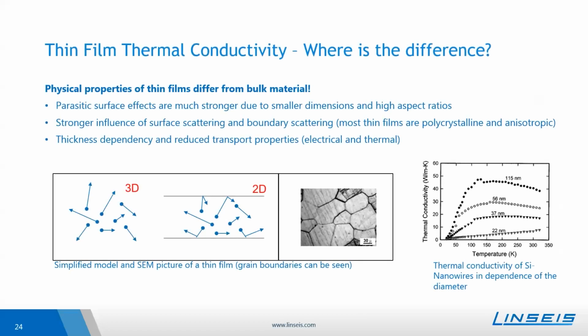Here maybe the question arises why thin film thermal conductivity needs to be separately typically analyzed. The main difference is also that thin film materials behave differently, like bulk materials, as parasitic surface effects are much stronger due to these smaller dimensions and the high aspect ratios. Furthermore, there's a stronger influence of surface scattering and boundary scattering, and the transport properties will just change due to the different thickness, so that it's also an important task to find out the properties of the bulk material and of the reduced size,